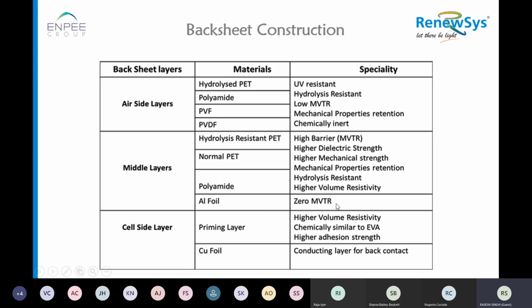This could also be a foil based back sheet, if the application of the back sheet is for highly sensitive cells like CIGS or thin film, which used to have a thin coating of photosensitive layer to be protected from moisture. Then the cell side layer of the back sheet should have better volume resistivity because it is going to face towards the cell. It should be chemically compatible with EVA because it is going to get adherence with the EVA, and it should have better cushioning and pliability to give support to the cell from cracking.